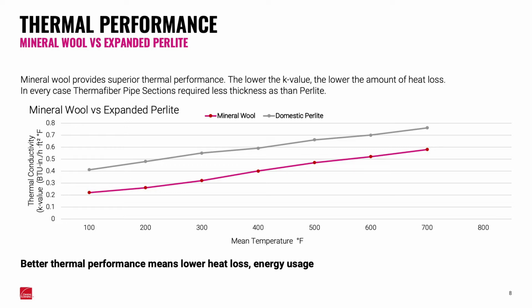So roughly, mineral wool has the same performance at half the thickness, or if you're looking at the same thickness for both materials, mineral wool performs twice as well as expanded perlite does. What that really means is better thermal performance means lower heat loss, less energy usage, and you don't need as much thickness of insulation for a given performance requirement. So in other words, you don't need as much thickness of mineral wool as you do with perlite. So again, better thermal performance, lower heat loss at a given thickness.